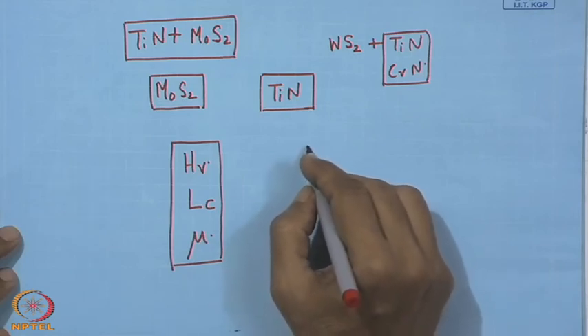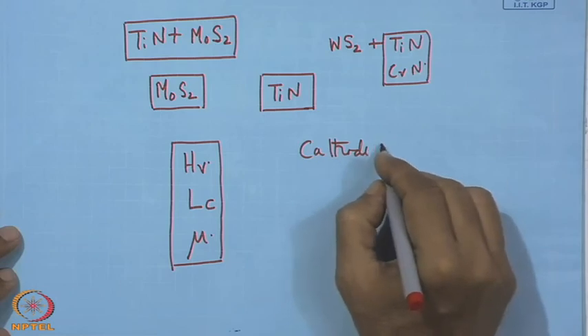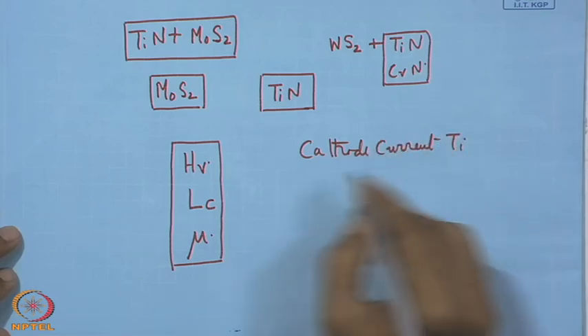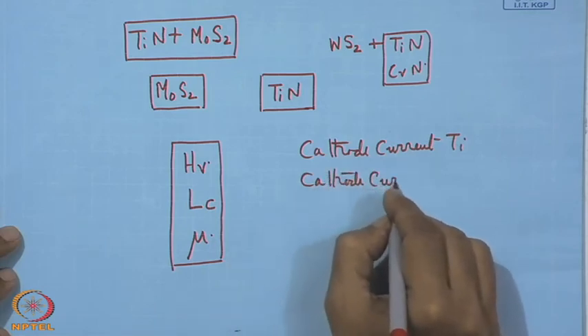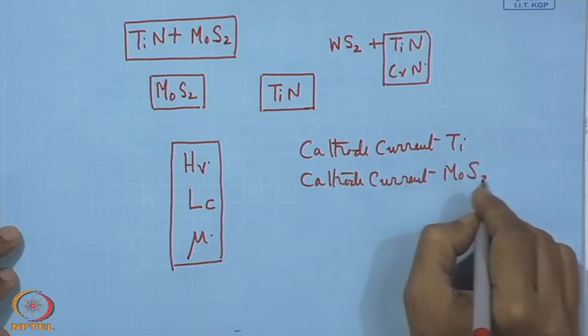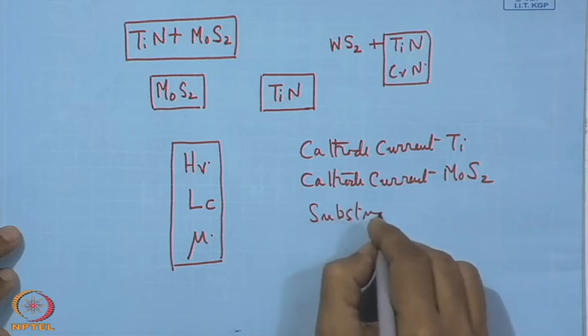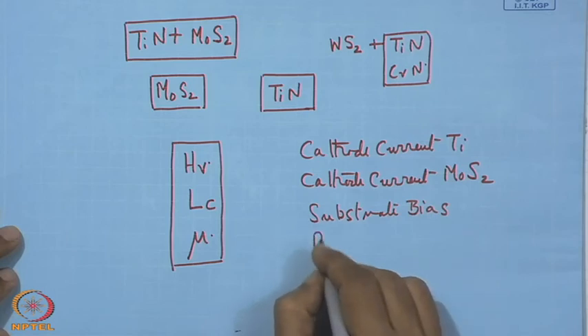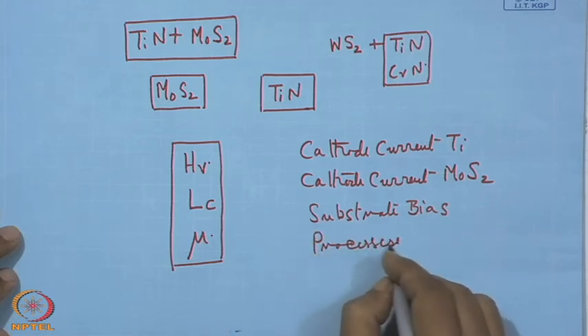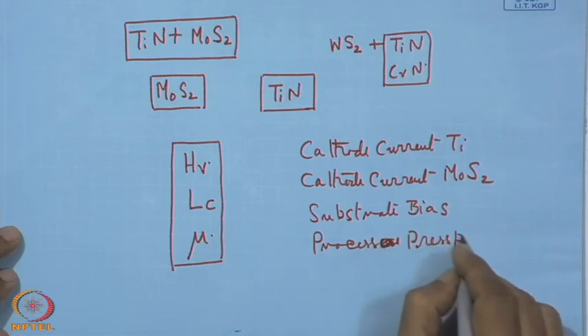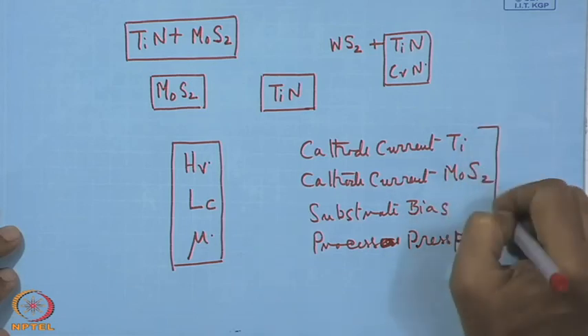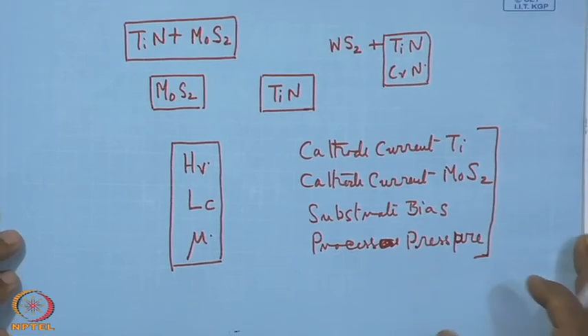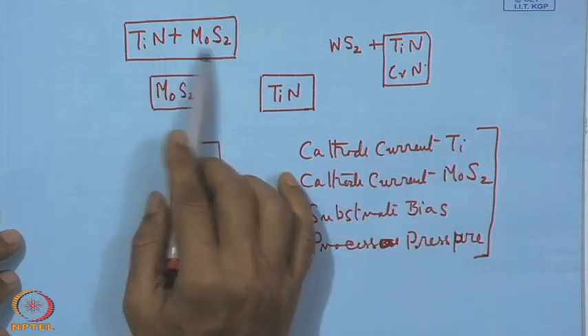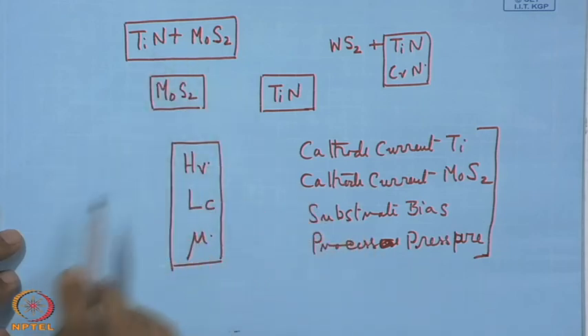And for that what we need, the cathode current for titanium, cathode current for MoS2, then the substrate bias, and process pressure. Keeping other thing constant means if it is a pulse DC, then pulse frequency for the target and the substrate, that is not altered. So, with this one can find out the best combination of these two things to get one of the best value of hardness of the coating, adhesion of the coating, and low value of the coefficient of friction.